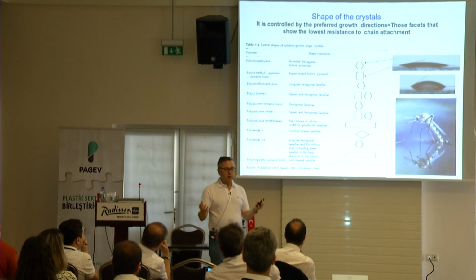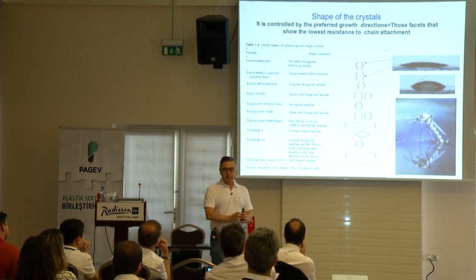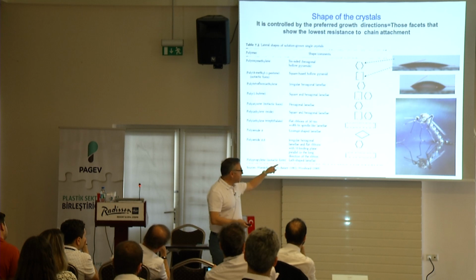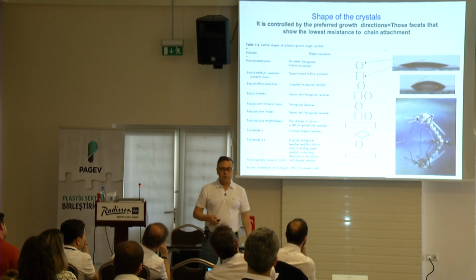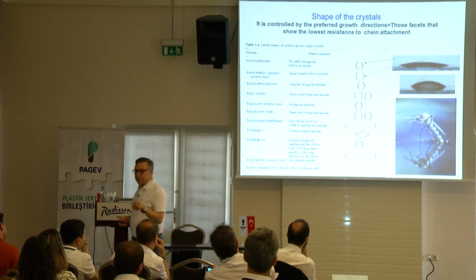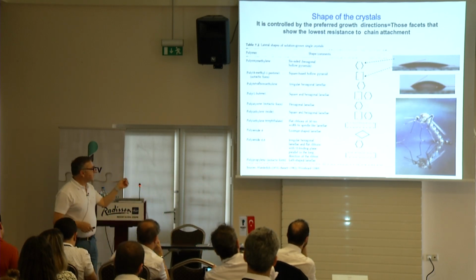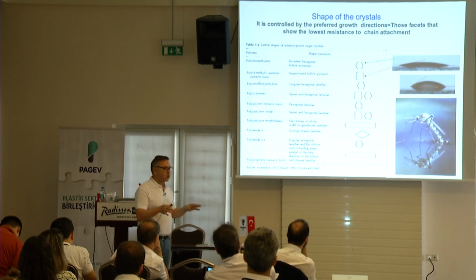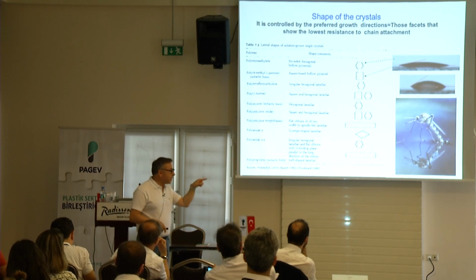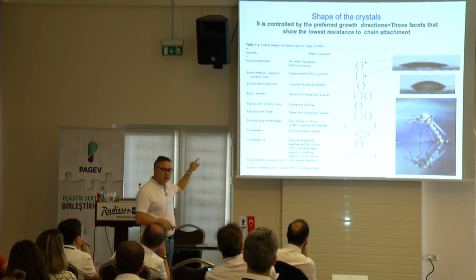So even though you're going into a lower energy state by crystallizing material, in order to take the polymer chain and put it on the surface, it costs you energy because you have to push through that barrier to go into the water. So that barrier is the surface tension. And that surface tension, in the case of water, is isotropic. It doesn't matter which direction. But in the crystals, it depends on the direction. Some directions are easier to penetrate than the other directions. As a result, you make shaped crystals.